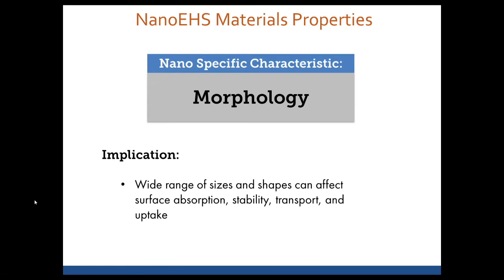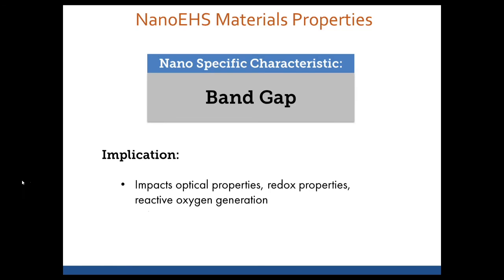The morphology is also important. Asbestos was a good example of a structure that became much more hazardous because of its shape. And there was a concern in the nanotoxicology space that the same thing would happen with nanomaterials. That was true to some extent, but in most cases it wasn't as dramatic as the asbestos example. So here we've got a wide range of sizes and shapes that can all affect surface absorption, stability, transport, and uptake.